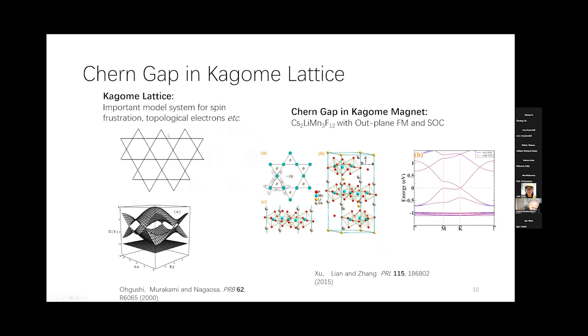On the other hand, if you use a tight binding model to calculate the band structure, you find it has 3 bands. One is a flat band, the other 2 bands are just like what is inside the honeycomb lattice, which has a band crossing point at the K point. So if you include the SOC and time reversal symmetry breaking with out-of-plane ferromagnetism, then you will open a gap on this touching point. Also, you achieve a Chern number equals 1 kagome quantum magnet. Actually, in 2015, Professor Zhang Shoucheng predicted some materials like this one. So if you have out-of-plane ferromagnetism and SOC, you open a small gap on this band crossing point.